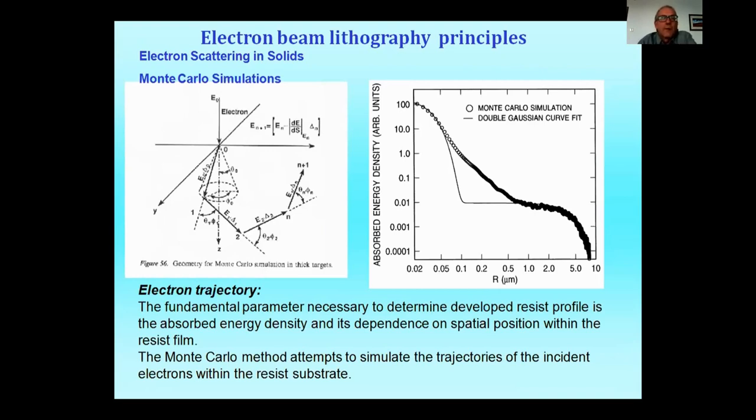Concerning electron beam simulation, there is a simple, or not so simple, statistical method, Monte Carlo, where electron trajectories are simulated along the resist and substrate. From such a method, we can determine the developed resist profile,